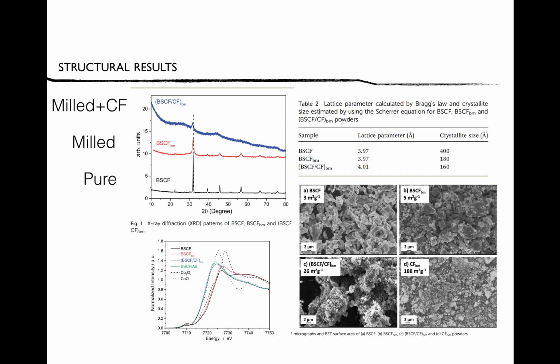There is only a 1.3 times difference in the size and in the surface area, although the size is slightly smaller. In detail, the population of particles under a certain range has increased, but it is not enough to increase the surface area too much, because the increase in surface area is only 1.3 times that of the unmilled sample.